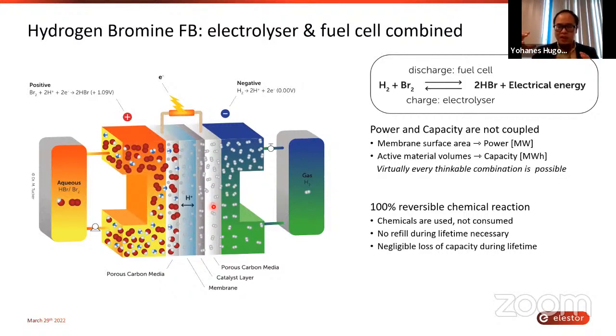So the bigger the electrode, the more power, but also the more energy it can store. But in our case, our electrode is inert, and the reactive material is present in the form of flowing media, the bromine electrolyte and the hydrogen. Our electrode is just the location for the electrochemical reaction to take place. So the membrane surface area will determine the power, including the electrode area, while the capacity will be determined by the volume of our tank, both the hydrogen and the bromine electrolyte.